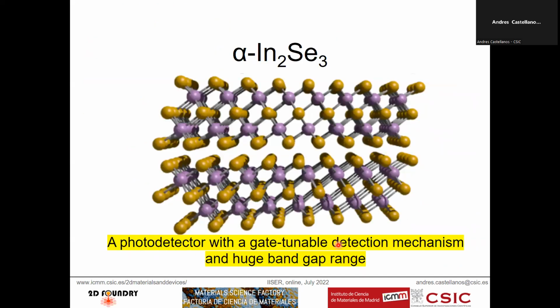So let's start talking about indium selenide. You have to notice that there are two different indium selenides depending on the stoichiometry. This is indium-2, selenium-3, but there is another layered semiconducting material, that is indium-1, selenium-1. Today I'm going to talk about this indium-2, selenium-3. What I find interesting about this material is that it is a photodetector with a gate tunable detection mechanism, and it has a huge bandgap range tunability depending on the thickness.